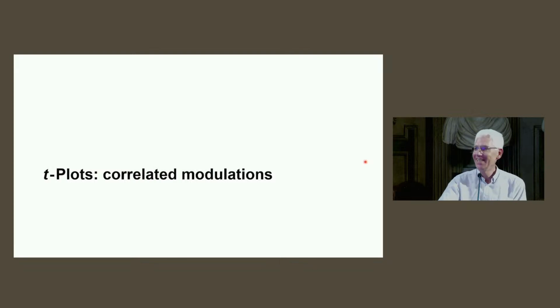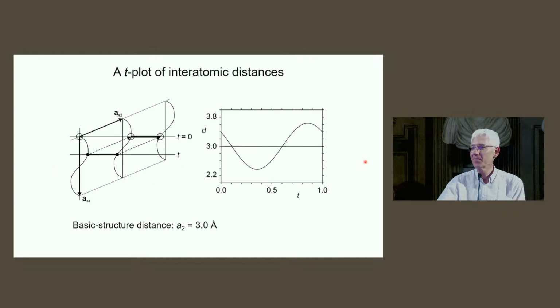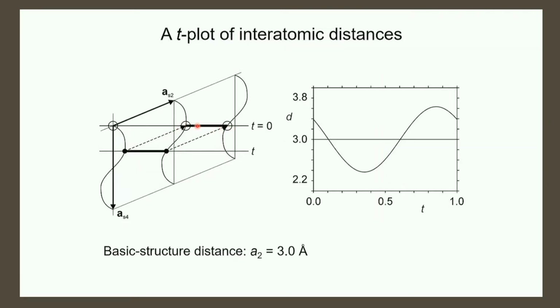No. So this T value, T plots, more than the shift of an atom, we are maybe interested in interatomic distances, and here it's indicated if we have a certain T, then we find this distance in our original physical space. Or the other way around, this distance in original physical space we find here at a different T in the first unit cell of superspace. So we can again shift T, and instead of a modulation wave, we now plot the distance. Also looks like a sinus, it's not. It's a bit different shape, difference of two sinuses.